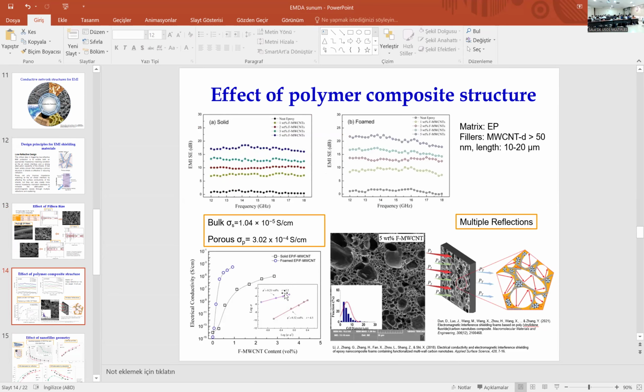And the effect of polymer composite structure can be seen here, in solid and foamed structure polymer composites. EMI performance and electrical conductivity of foamed and solid polymer composites are compared here. Compared to solid polymers, foamed polymers exhibit good electrical conductivity with a lower filler content. It was demonstrated that foaming makes the carbon nanofiller redistribute and orient around the cells, resulting in more efficient interconnected conductive pathways throughout the composites.